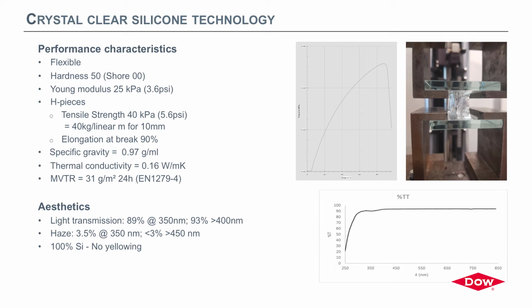As we don't have a filler, we also have a much better thermal conductivity. So, as you know, filled silicones are stated at a lambda value of 0.35 watt per meter Kelvin per ISO 10456. So here we are at 0.16 watt per meter Kelvin. We also verified the moisture vapor transmission rate. So this one is at 31 grams per square meter per 24 hours.